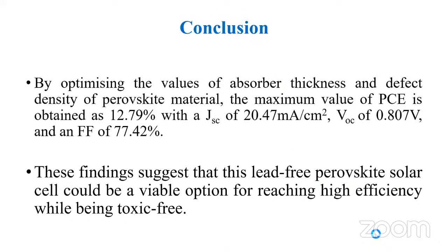This is the conclusion. By optimizing the absorber thickness and the defect density of the perovskite material, the maximum power conversion efficiency obtained is 12.79%, with a JSC of 20.47, VOC of 0.807 volt and fill factor of 77.42%. These findings suggest that this lead-free perovskite solar cell could be a viable option for reaching high efficiency while being toxic-free.